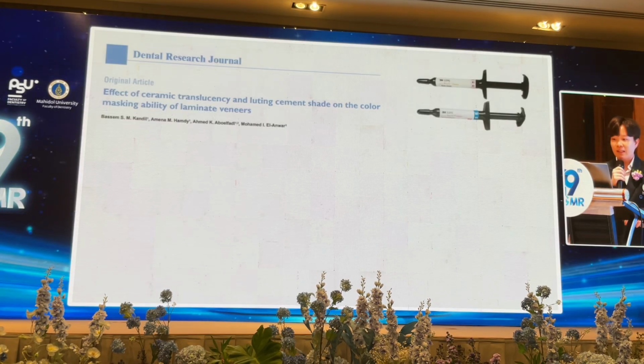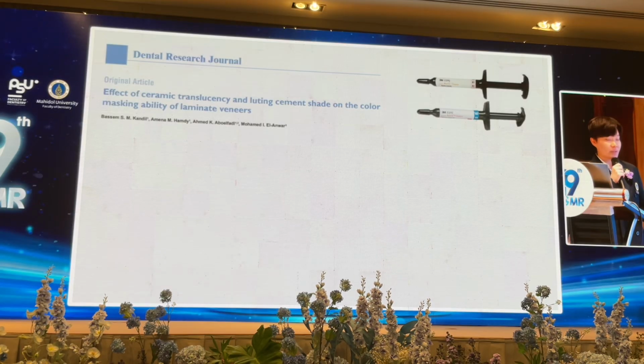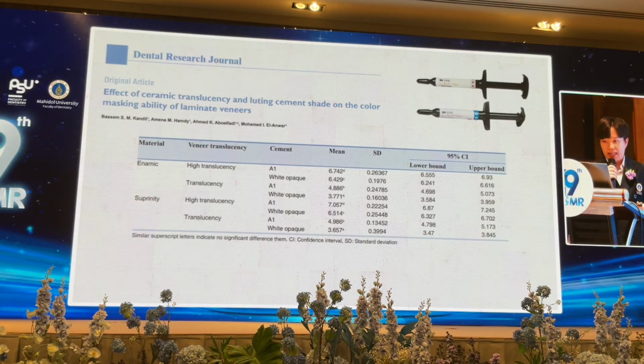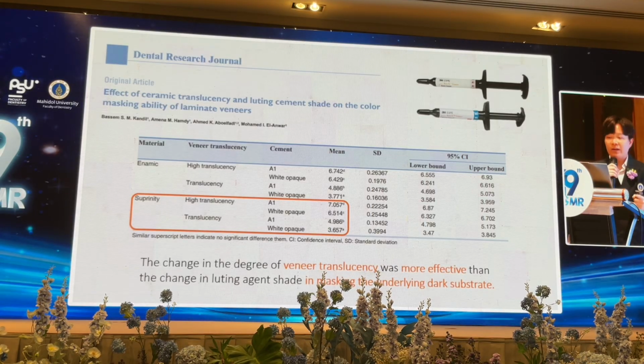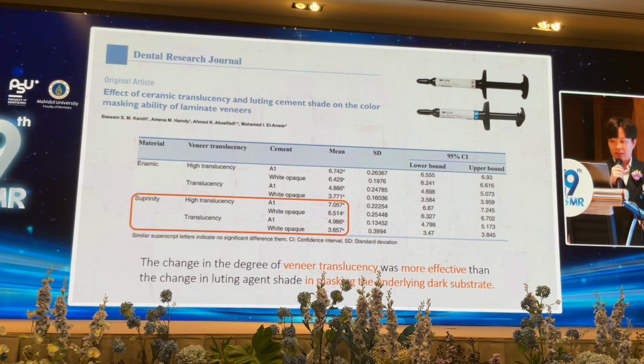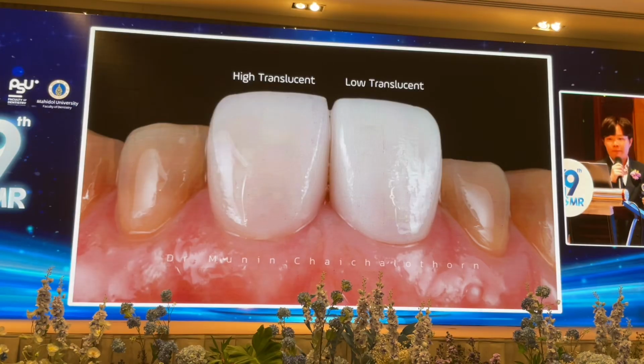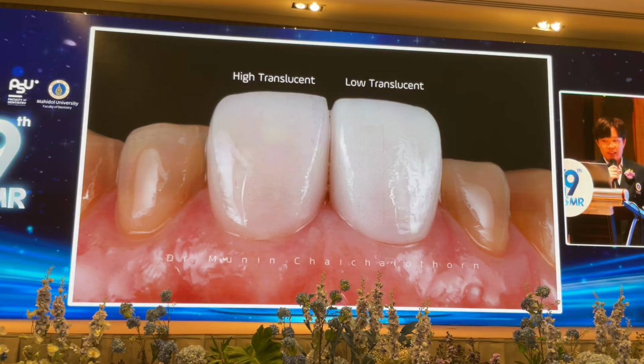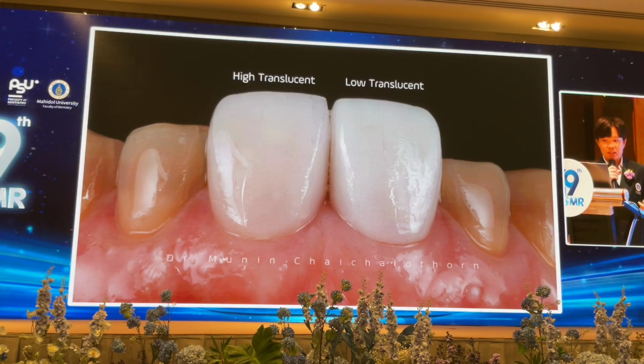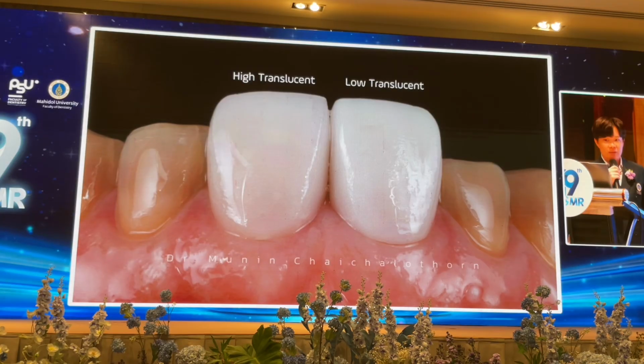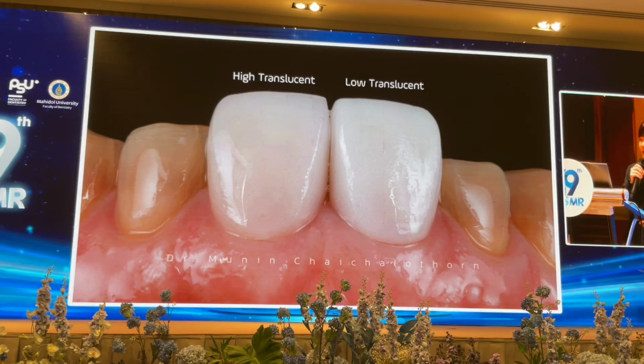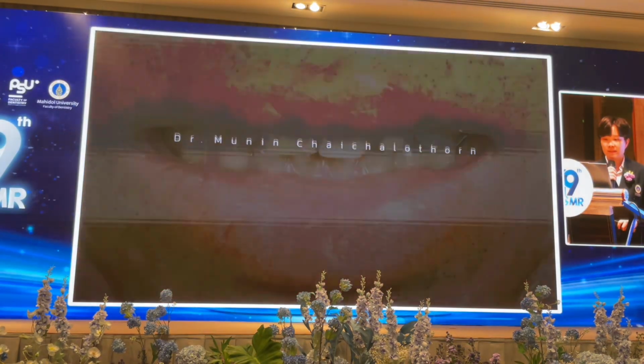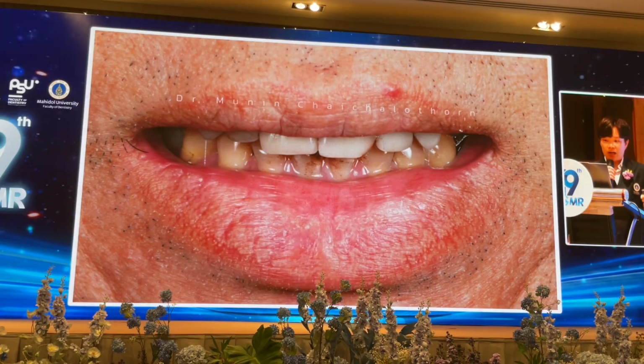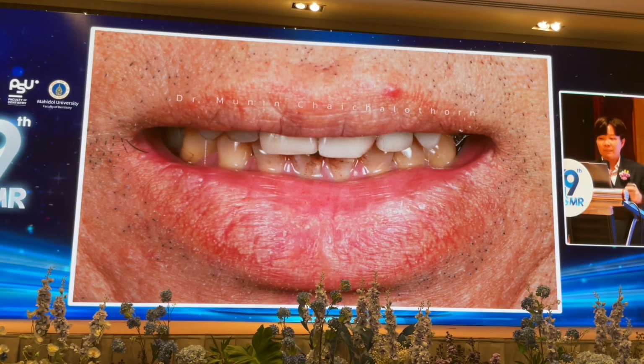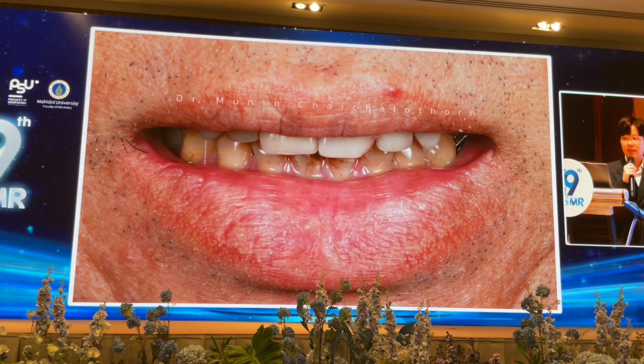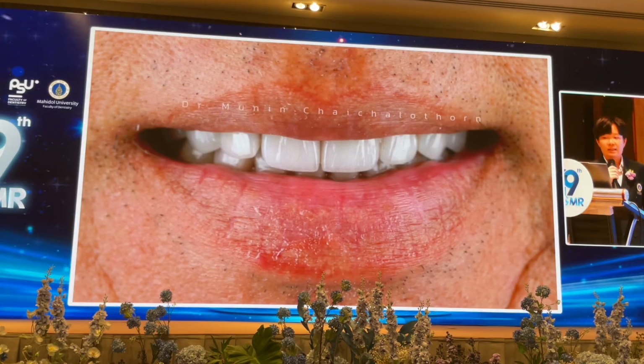And this study observed the color masking ability of different ceramic translucency and resin cement shades. The results show that changing the veneer opacity is actually more effective than changing the luting agent opacity when it comes to masking a dark underlying substrate. And take a look here. When we put veneers on a dark abutment, notice how the abutment color shines through the ceramic veneer, especially for the high translucent ceramic. And this changes how the final restoration looks. So, for the case where there is a dark abutment, with the combination of low translucent ceramic and opaque resin cement, we can transform it into a natural and beautiful smile.